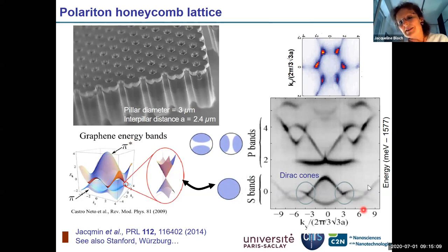Here, if you look just at the lowest part of the dispersion that you can measure in such a lattice, you see directly the very characteristic band structure of graphene with Dirac cones. And if you look at the emission at exactly this energy as a function of Kx and Ky, you see directly the six Dirac points, the first Brillouin zone, and so on. So we have really an emulator of the physics of a graphene layer. We have actually more than that, because we also have these bands which emerge from the hybridization of the p orbitals, where there is also a lot of very interesting physics to develop. We have a flat band here, we have new Dirac cones, so we did actually a lot of things studying this physics in polariton honeycomb lattices.